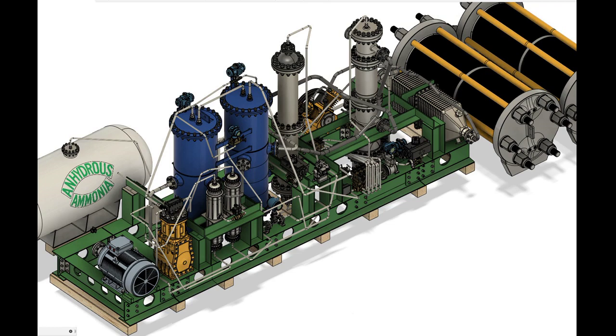This microporous insulation can maintain a low thermal conductivity of 0.023 watts per meter Kelvin at a temperature of 300 degrees Celsius, increasing to only 0.03 watts per meter Kelvin at 600 degrees Celsius, 150 degrees hotter than what is encountered in a Haber-Bosch reactor. Unifrax, located in Tonawanda, New York, offers a flexible microporous insulation called Excelfrax 1800 FlexLiner, which can be conveniently wrapped around cylindrical components or hoses, without custom shaping.